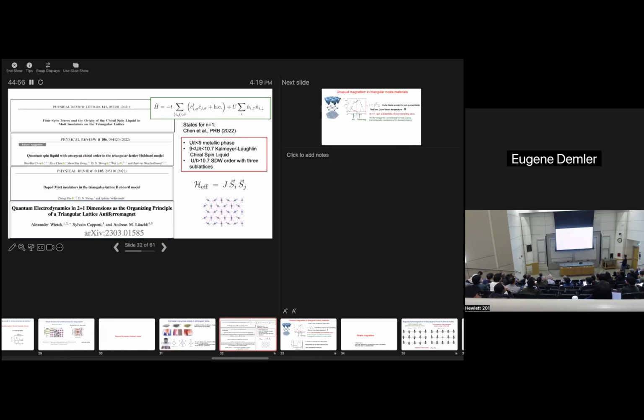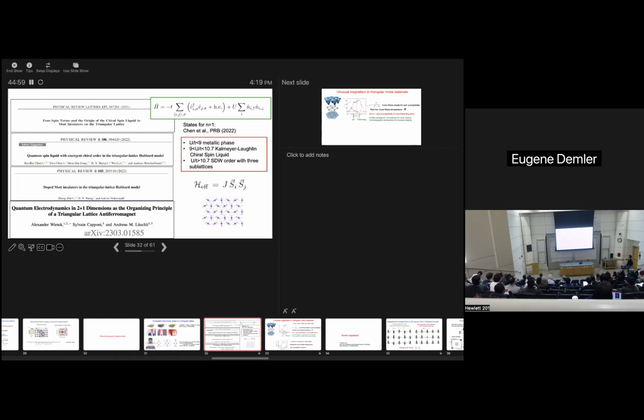Okay, and so actually magnetism in triangular lattices has been a subject of a lot of interest to theorists. There have been many suggestions, and one of the new features is that when interaction is weak, then one doesn't even find magnetic order, there is not even insulating behavior. It's a metal, then there is a phase suggested by Bob Laughlin quite some time ago, and only at very large interaction do we go back to this antiferromagnetic Heisenberg picture in which spins align with this 120-degree pattern.